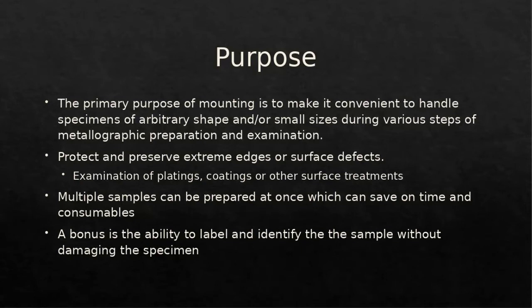And so the higher the magnification you analyze your sample, especially around the edges, it'll look very rounded. If you're looking at coatings that are supposed to have a minimum thickness requirement, this would be a very poor way of looking at that surface, because with that edge being round, most definitely you're going to have a much thinner measurement of that coating or plating than you would have by mounting it.